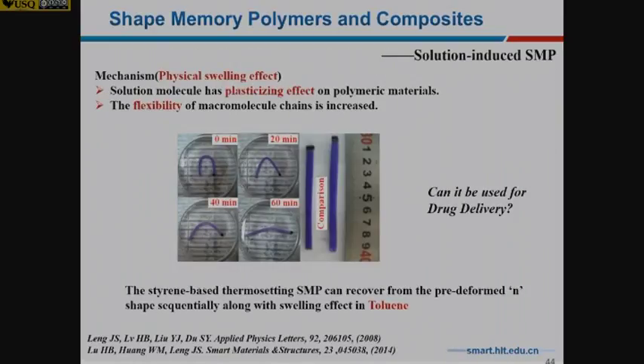The polymer can also be driven by stimulus, different solutions. We found this phenomenon very early with some colleagues in Singapore. You see this physical swelling effect from 0 minutes to 60 minutes. The polymer can deploy very easily, but it's not only shape changing, it also changes dimensions, which means in the future, if you have a drug inside the tube, it can do some drug delivery.